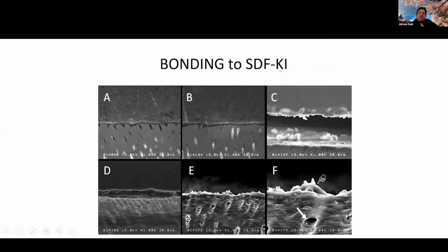So people also ask about potassium iodide and SDF. Unfortunately, if you apply potassium iodide after silver diamine fluoride, it is very hard to bond to that kind of dentin. So if your plan is to use adhesive right after application of SDF, do not even think of doing potassium iodide because it creates a creamy precipitate, which is so difficult to remove. So unless you have a plan to physically remove dentin after potassium iodide, you won't be able to bond to that structure. And this is what we published last year in the American Journal of Dentistry.